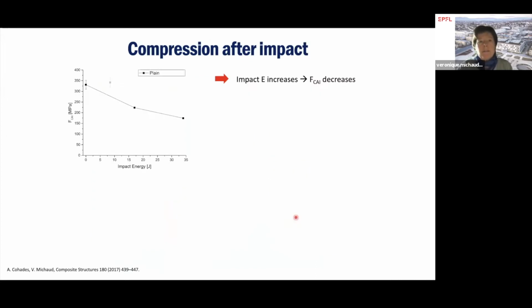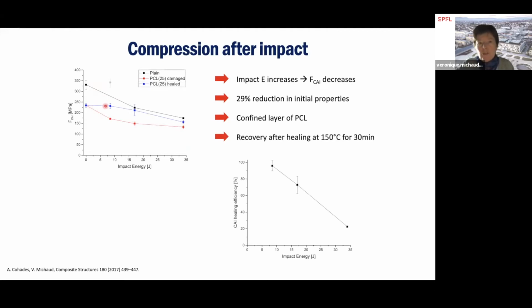We did compression after impact tests to show that the compression after impact of the composite with the PCL is actually lower than that of the plain reference composite, of course, as the material is a little bit reduced in properties. But after healing, we have this blue curve that shows that the healed material after impact, of course, this one you don't heal because it's a normal epoxy. This one, if you do an impact at this energy and then you heal up, you will almost recover the properties of the pristine composite after impact. So it was encouraging. Of course, this is not yet perfect, but we could see that it works.